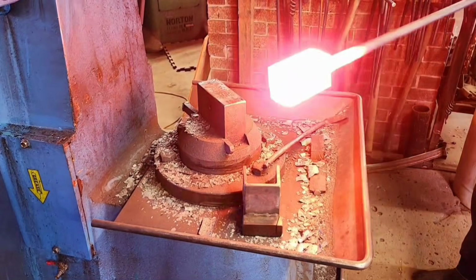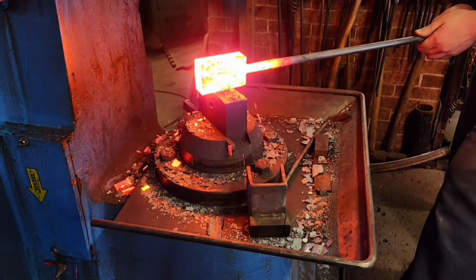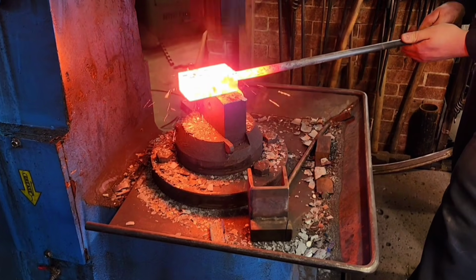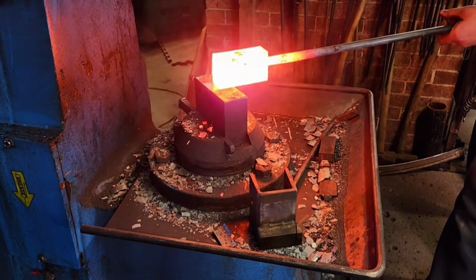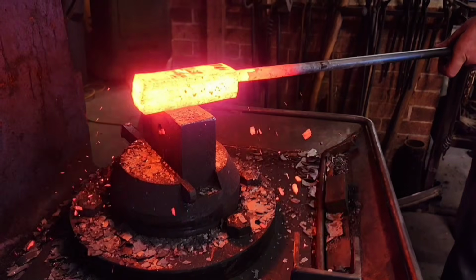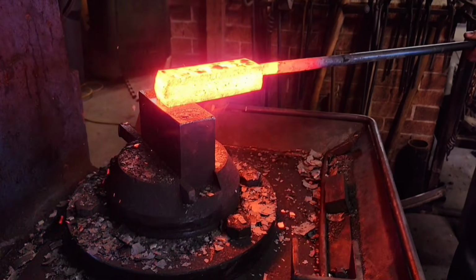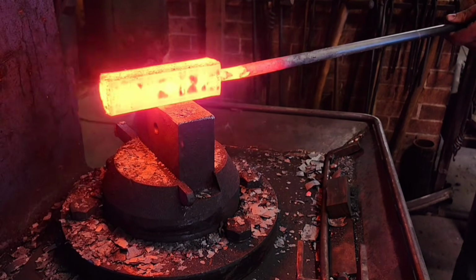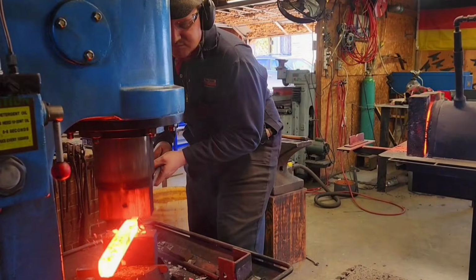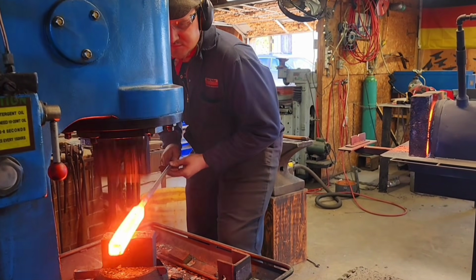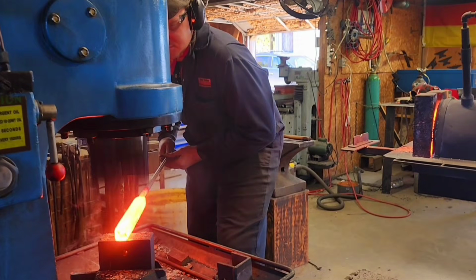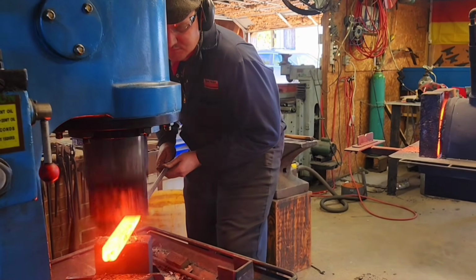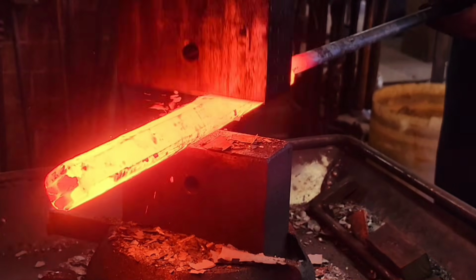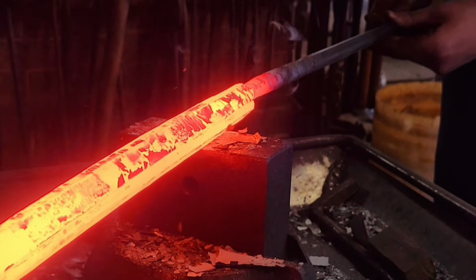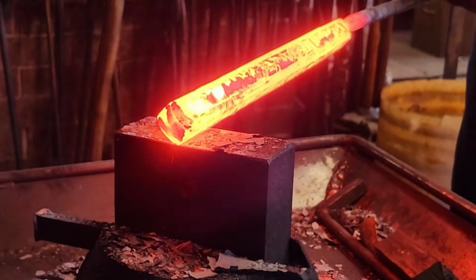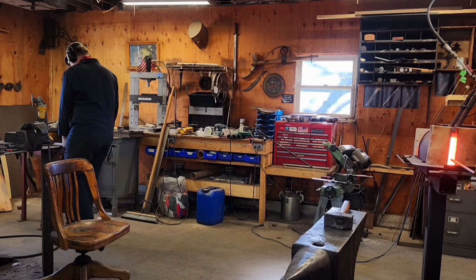Once we have a nice welding temperature, we're going to forge weld these 3 pieces together. You can always tell if it's the right temperature if there's a little bit of steam coming around the billet. This is evaporating the liquid in the air. Now here I am forging it pretty much square. And then I'm going to knock these corners in, so it's going to be slightly octagonal. This will really help when we go to twist the bar.